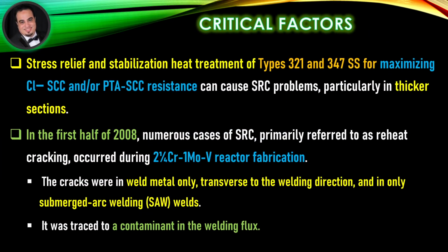Stress relief and stabilization heat treatment of types 321 and 347 stainless steel, for maximizing chloride stress corrosion cracking and/or polythionic acid stress corrosion cracking resistance, can cause stress relaxation cracking problems, particularly in thicker sections. In the first half of 2008, numerous cases of stress relaxation cracking, primarily referred to as reheat cracking, occurred during 2¼ chromium 1 molybdenum vanadium reactor fabrication. The cracks were in weld metal only, transverse to the welding direction, and in only submerged arc welding welds. It was traced to a contaminant in the welding flux.